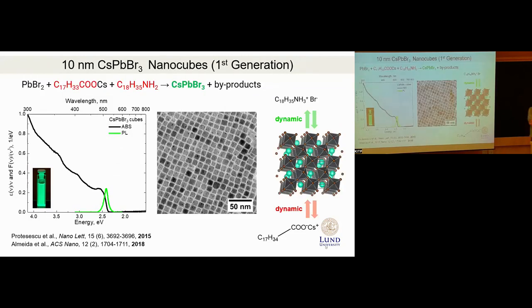So we started our work with this first generation of perovskite nanocubes, made by the method essentially developed by Kovalenko group in Zurich. So it involves reaction of solubilized lead bromide with cesium oleate. As a result, we form these about 10 nanometer edge nanocubes, which are passivated by octadecylammonium bromide and oleic acid or cesium oleate, which are in dynamic equilibrium. So this is one difference from, for example, lead sulfide or cadmium selenide particles, where ligands are much more tightly bound. With perovskites, since interactions are ionic, the ligands attach and detach in the solution.